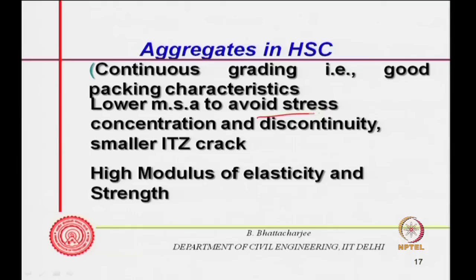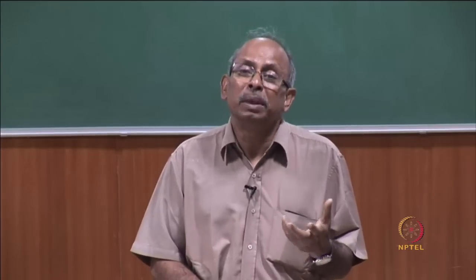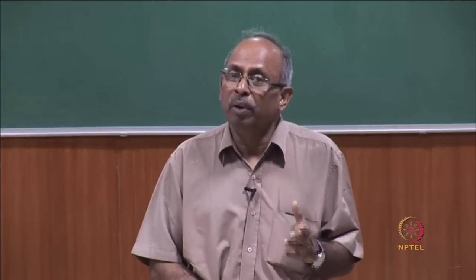So, lower MSA obviously, to avoid stress concentration and discontinuity you have talked about. So, MSA will be lower, good packing characteristics, best packing density I will say, and then it must have high modulus and high strength, because if its strength is lower, this can restrict the strength of the concrete system itself. It is the weakest link. So, use a poor aggregate, and even if you improve the paste strength, it is not going to help. Therefore, your aggregate must have high modulus and high strength.